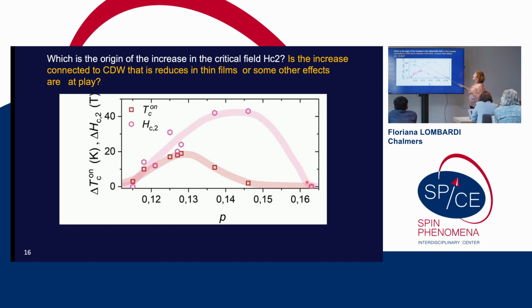Essentially, we believe that the charge density wave and the increase of HC2 are kind of disentangled, because this is the increase in TC in thin films as a function of doping, and we also plot the increase in HC2 compared to thick films in our thin films as a function of doping. And you see that the maximum increase in the HC2 happens here at a doping where you don't yet get a strong increase of the superconducting temperature. And this somehow tells that the two things are kind of disentangled.